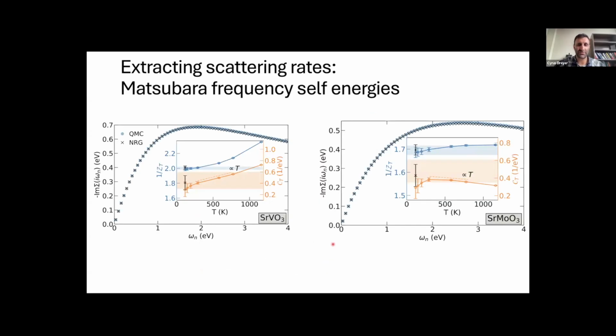And so we've also done this for strontium vanadate and strontium molybdate. Here again are just the self-energies, and in the insets, the points are the convergence of C for the orange and Z for the blue as we go down to lower and lower temperatures. We can see that we start to increase our numerical errors as we decrease temperature, but basically they're still consistent with these blue and orange bars, which correspond to the Z and the C that we get from the real frequency data. So overall, we have consistency between QMC, between NRG, between real frequency, and between imaginary frequency. And so together, we can have confidence that we have minimized as far as possible our numerical errors.